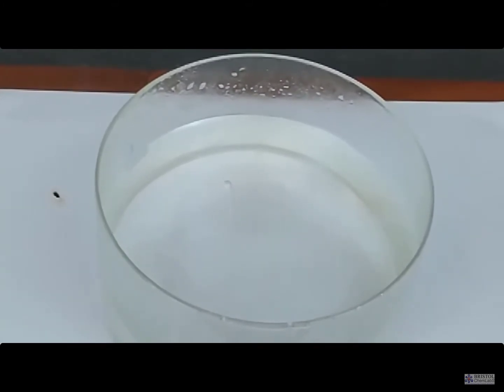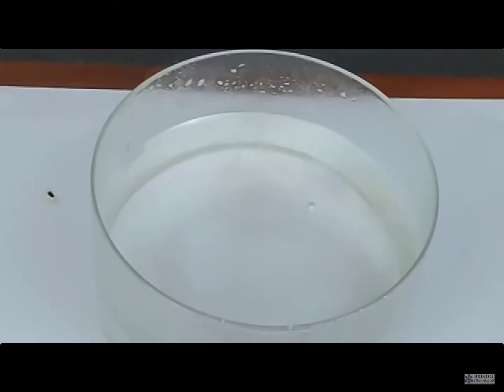In the first experiment, the typical experiment, we put a small lentil-sized piece of sodium into the water. This is a very clean trough, and we'll see the sodium do a number of things. The first is it floats. Sodium has a low density. Secondly, the reaction with water is such that the sodium metal reshapes and becomes a ball of molten sodium. I think the melting point of sodium is somewhere near 98 degrees centigrade. There's also gas produced, which of course is hydrogen, and that propels the globule of sodium across the surface of the water.